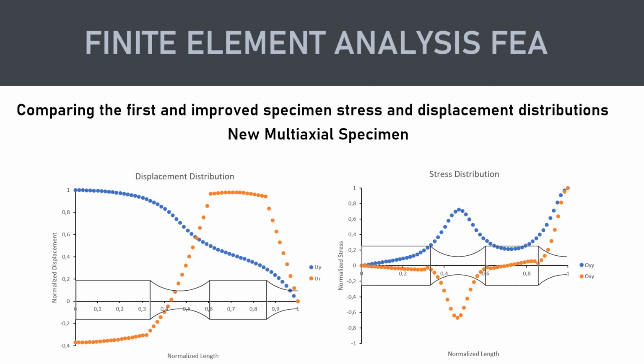Now, looking at the new geometry, we're able to increase the rotation. We can clearly see the rotation is much higher in the cylindrical sections between the main throat, which leads to a higher shear stress in the main throat, and therefore the combination is higher in the main throat, not just because of the actual stress but also in the shear stress. This increase in rotation, this manipulation of rotation, creates the ability to change the relation between the torsion and the tension.